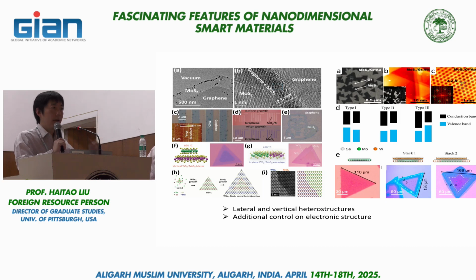Okay? You can also do it in another way. You grow one whole monolayer of one TMD, cover the whole surface, and then you switch to a different precursor. In that case, you will grow another layer on top of the existing layer. So that is a heterostructure in a vertical direction. So you can get lateral heterostructure or vertical heterostructure.